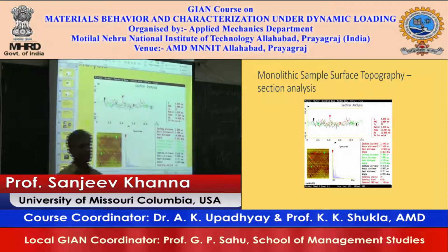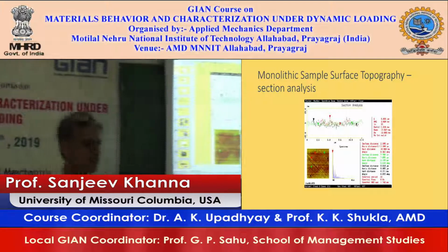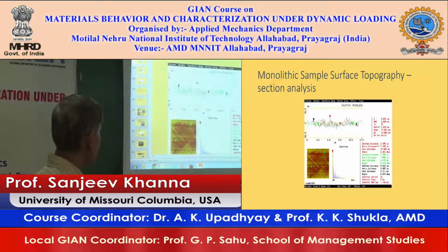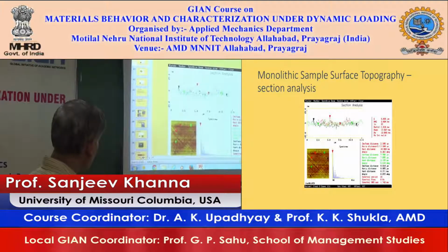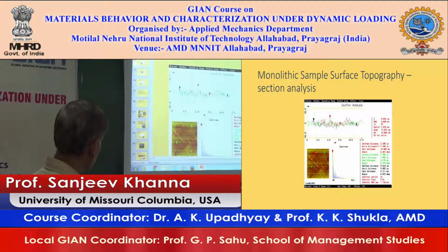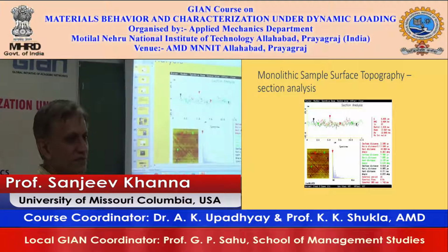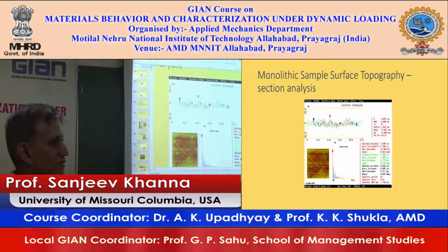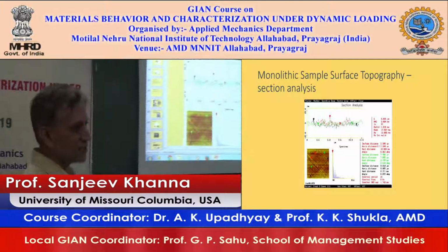So our goal was to get anything around 10 nanometers or below. We were actually getting much less than that. And then we scanned between these 2 points, and this point at different places to see if we get uniform root mean square surface roughness of less than 10 nanometers.